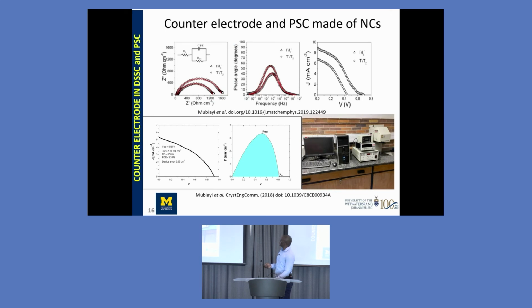So we went on also checking what is happening at the counter electrodes. And I said in the previous slide that counter electrodes are mostly made of expensive metals such as gold, such as platinum, and so on. So we replaced gold, platinum, and silver by cheaper material. Carbon-containing materials are always cheaper because they're everywhere and easy to get. So we replaced them and we coupled them with the nanocrystals. And the specific nanocrystals that was used here was cesium tin zinc bromide. And when we group the nanocrystals with the carbon-containing material, which is reduced graphene oxide, we make nanocomposites.